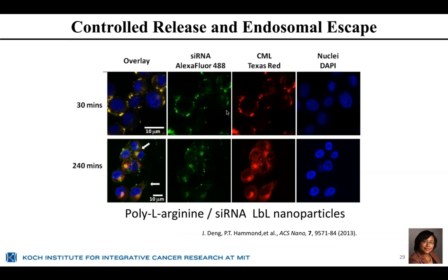This is also the direct result of buffering effects in our layer-by-layer film, in this case induced by the presence of poly-L-arginine. And the way that it works is that the nanoparticle, when it's first taken up in the cell, is taken up in an endosome, a vesicle which has a pH which is getting lowered from 7 to 6.5 to 5.5. And as the pH is being lowered in this endosomal compartment, essentially we're seeing the opportunity for these nanoparticles to also undergo buffering. And in that buffering process, they actually create some small leaks in the endosomal compartments, and we get endosomal escape.